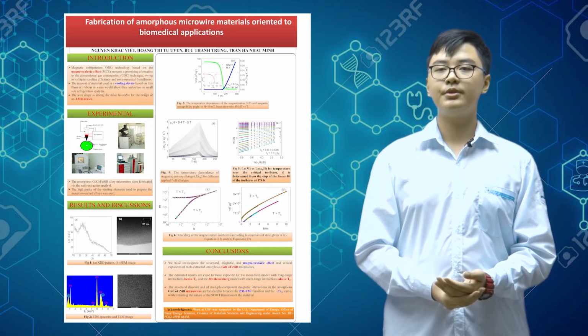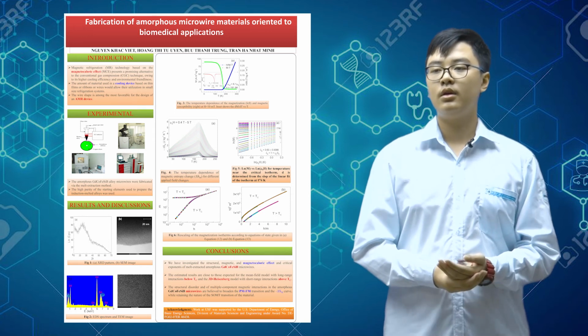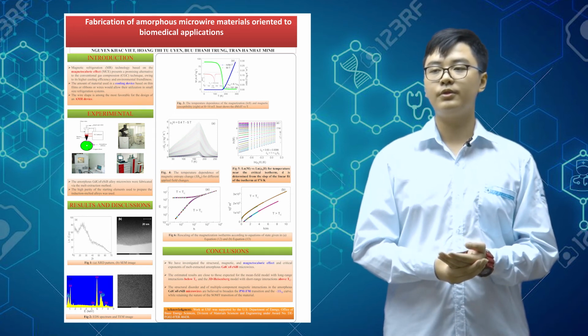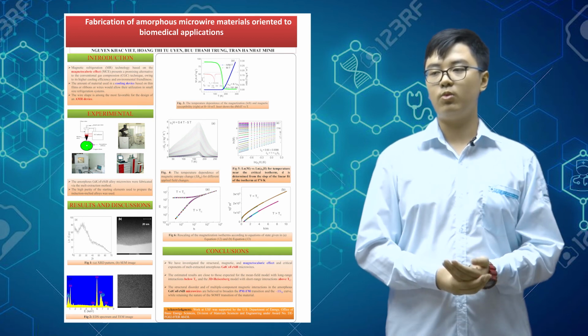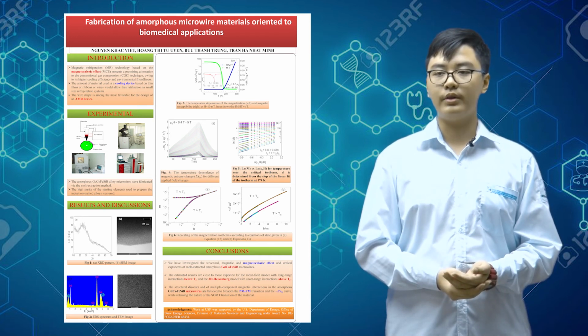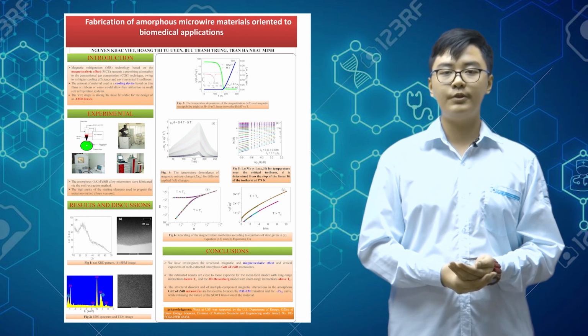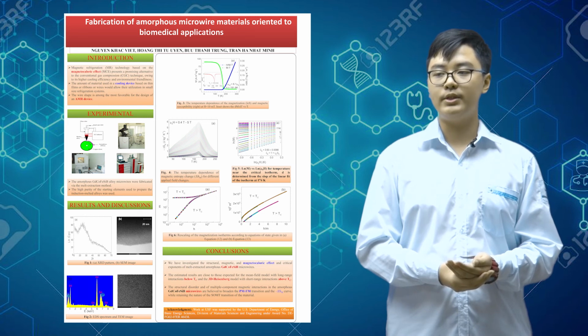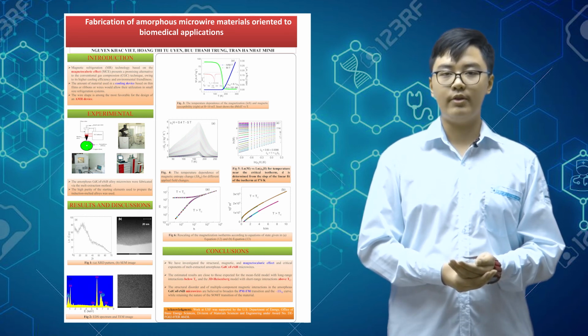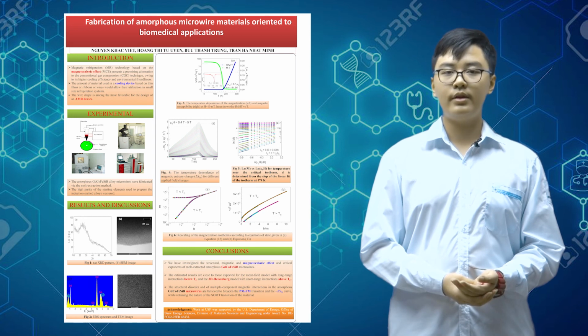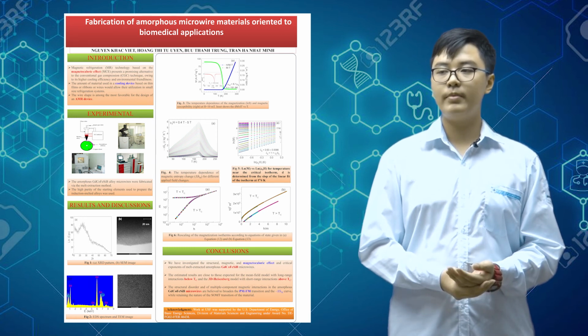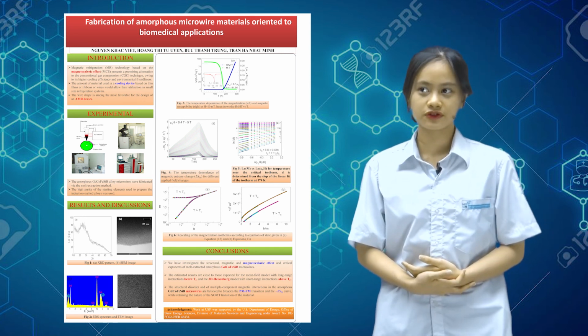Figure 6 shows the rescaling of the magnetization, with good linearity with beta equals 0.493, gamma equals 1.321, and Tc equals 174 Kelvin. We calculated delta equals 3.678, so the three critical exponents obtained by the Kouvel-Fisher method are beta equals 0.493, gamma equals 1.321, and delta equals 3.678. From this figure, a good collapse of the rescaled magnetization is achieved, confirming the correctness of the critical exponents obtained from the Kouvel-Fisher method. Finally, we conclude our research.